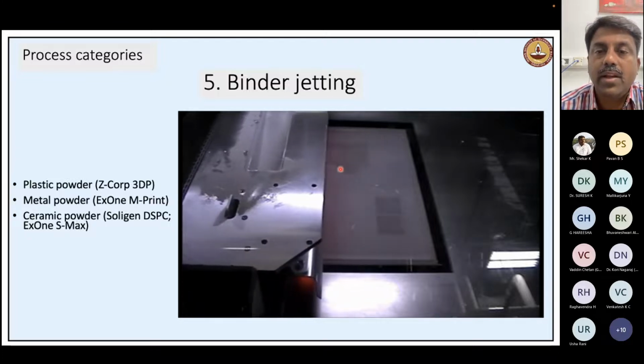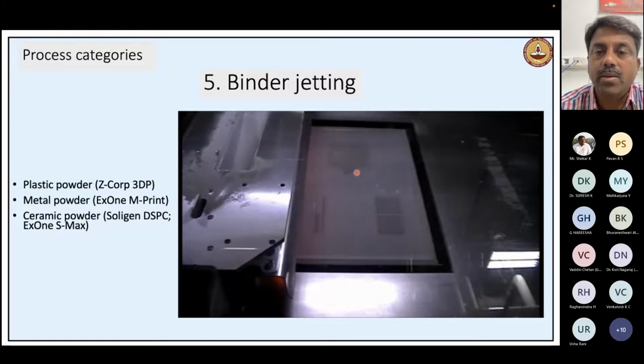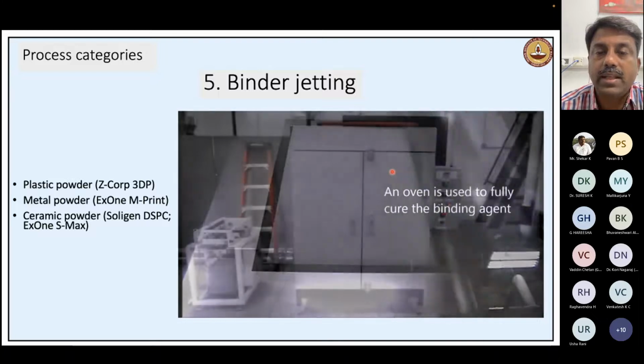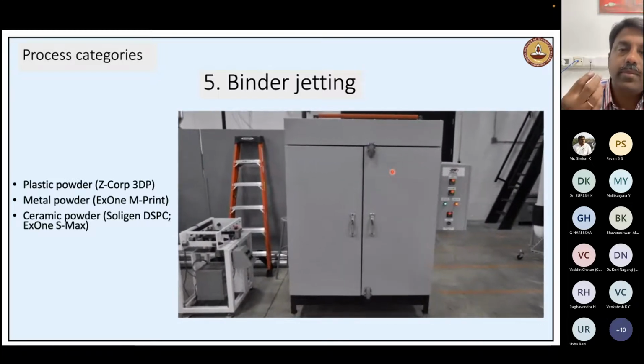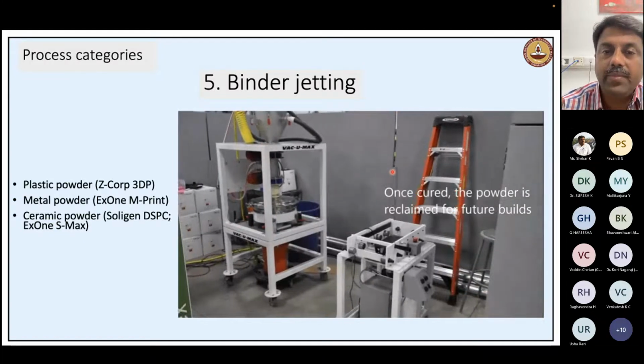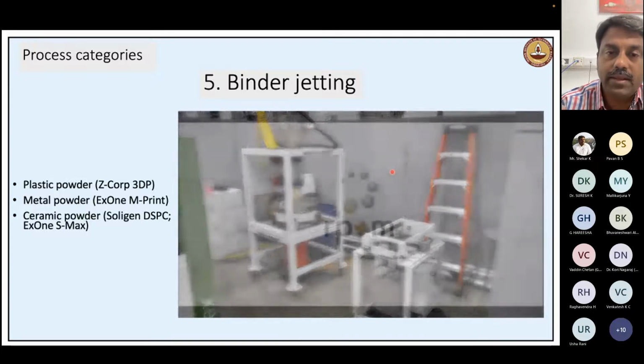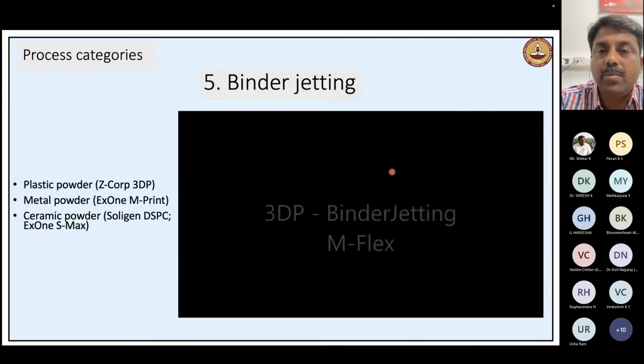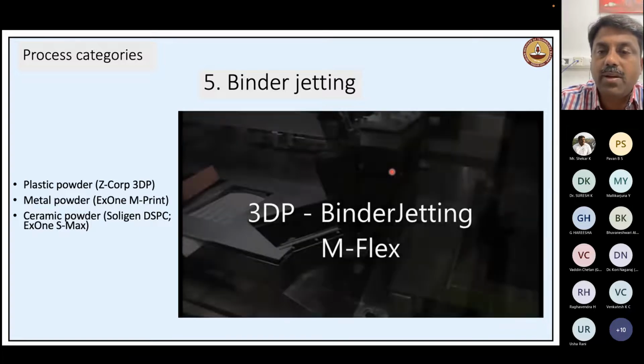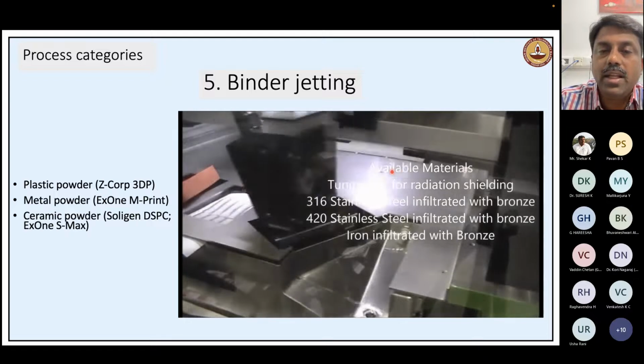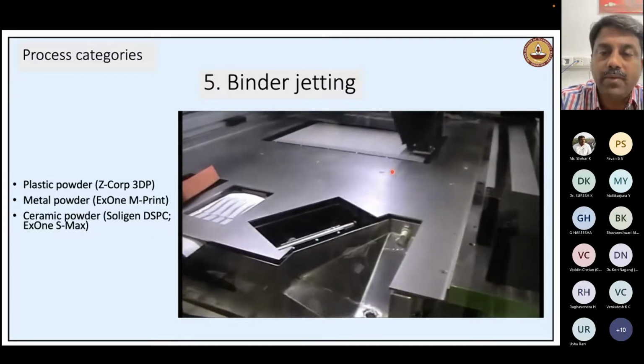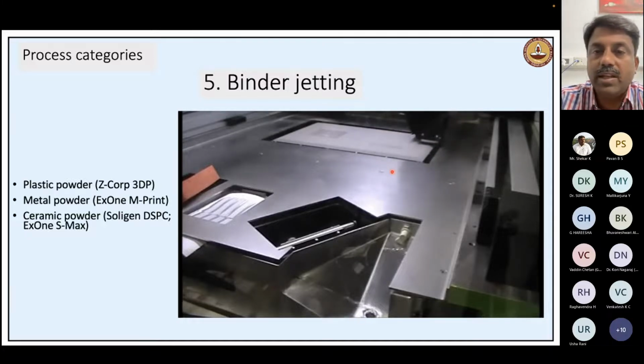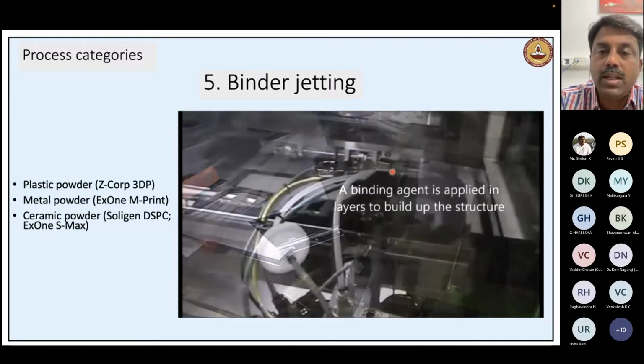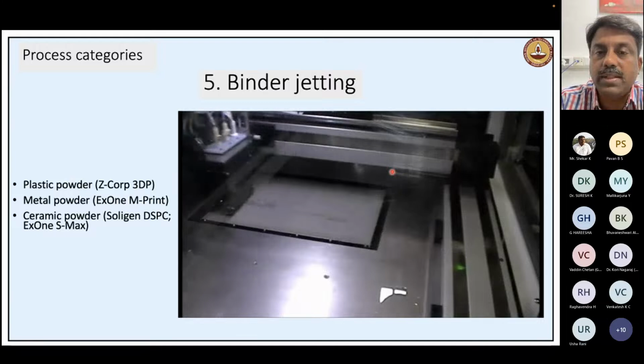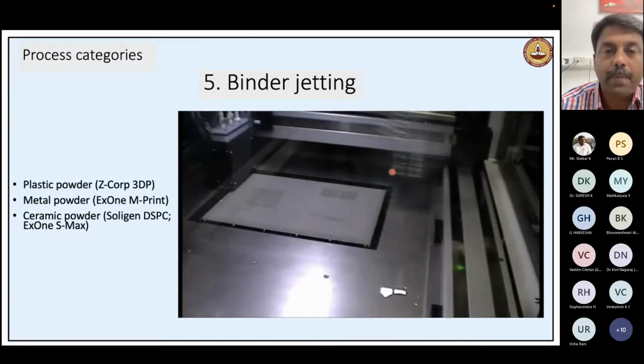The binder is creating an agglomeration at the locations where binder is present. Then subsequently the next layer of powder is added, and what we create is the part which we call the green part. Then we can take the green part out, place it in an oven, and further sinter it to get a final component. We can also create ceramic components here, hard materials, because we are not melting anything. The tungsten carbide cobalt ceramic tool we can effectively produce here by creating a feedstock mixture of tungsten carbide and cobalt, then adding binders, and then subsequently doing a post-process sintering, to get a nice ceramic tool.